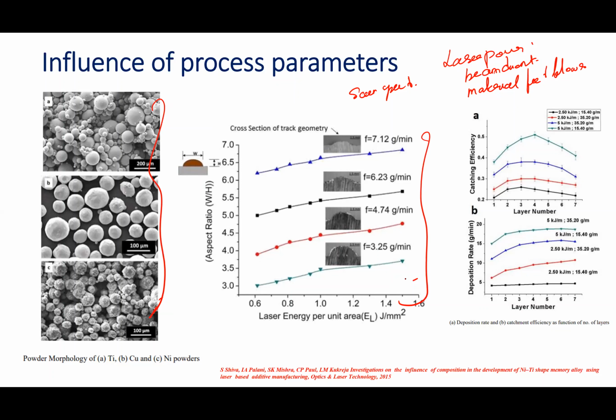This is because some minimum amount of laser energy is needed to accomplish two physical processes in the laser material interaction: melting of the feed powder and wetting of the thin layer of the previously deposited material. In the case of the brick shaped structure, only process parameters yielding uniform and regular shape were screened in, and as the powder feed increased, the laser energy per unit area was considered to be around 0.1 kilojoule per mm square. As the powder feed increased, the laser energy also needed to be increased, as more laser energy is required to melt the powder fed at a high powder feed per unit area.